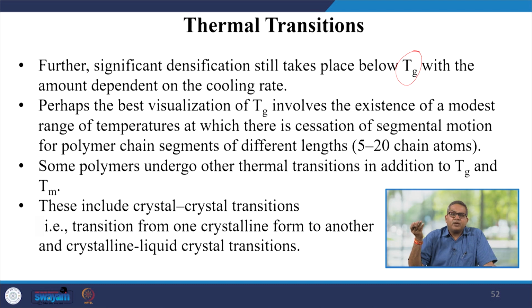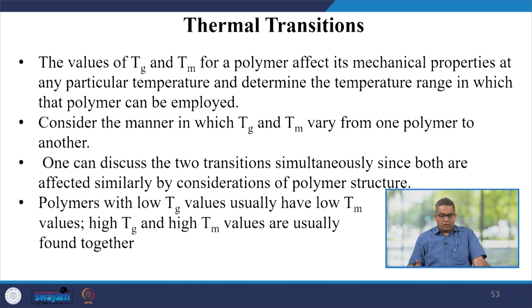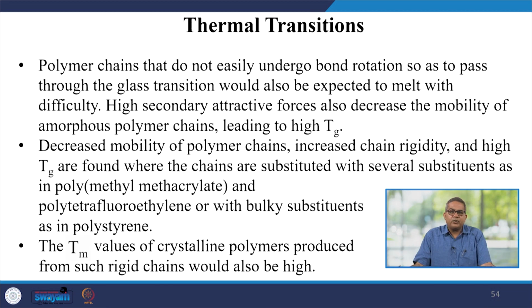Now, some polymers may undergo thermal transitions in addition to glass transition and Tm, and this includes the crystal-crystal transitions. The values of glass transition temperature and Tm for a polymer affect the mechanical properties at any particular temperature and determine the temperature range in which the polymer can be employed. Let us consider the manner in which the Tg and Tm vary from one polymer to another. One can discuss the two transitions simultaneously since both are affected similarly by consideration of polymer structures. So, polymers having low glass transition values usually have low Tm values, and high Tg and high Tm values are usually found together.